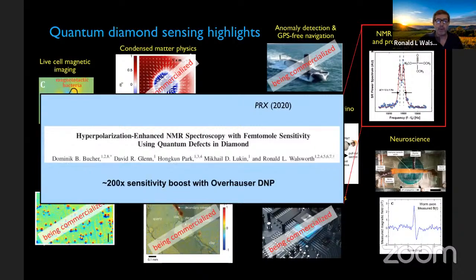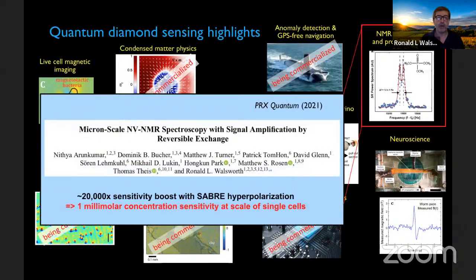In 2020, we showed a 200x sensitivity boost. And by last year, we've now gotten about a 20,000-fold sensitivity boost using a technique known as SABRE hyperpolarization. This now got us down to about 1 millimolar concentration sensitivity at this 10 micron scale. That's pretty good. We want to still get down into the micromolar scale and then apply it to individual cells.